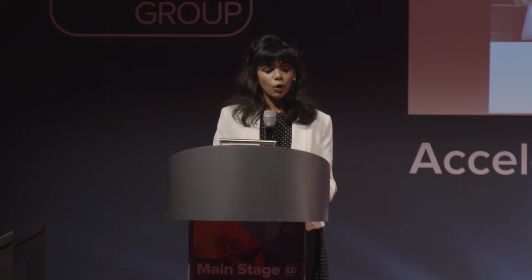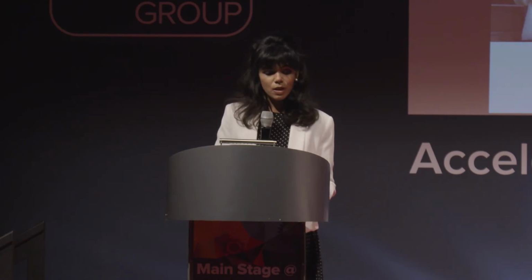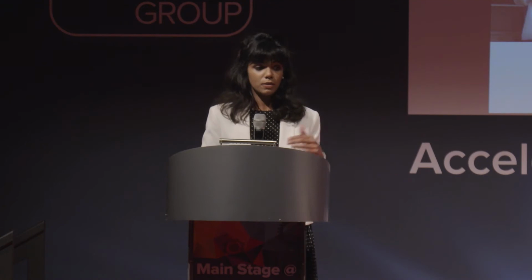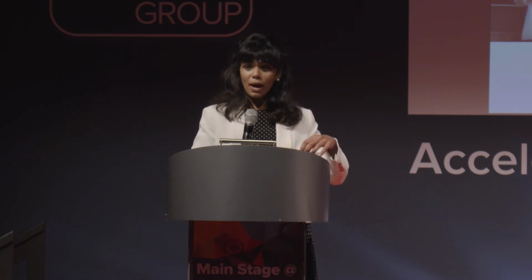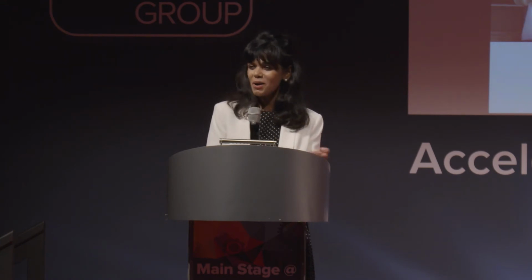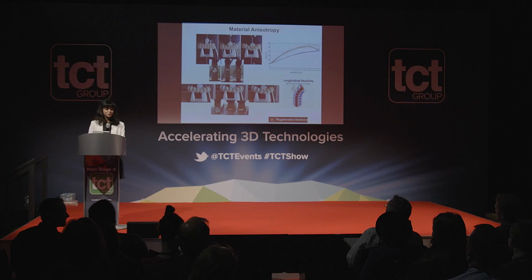If you know, the trachea is longitudinally flexible, so you can move your head, but it has to be radially rigid. So we applied mechanical forces to the places where it should bend, and it bends accordingly. One of the problems with other methods is that it's not flexible, but just, how shall I say, bends in half. It should move without closure of the lumen. So that's what we wanted to create.